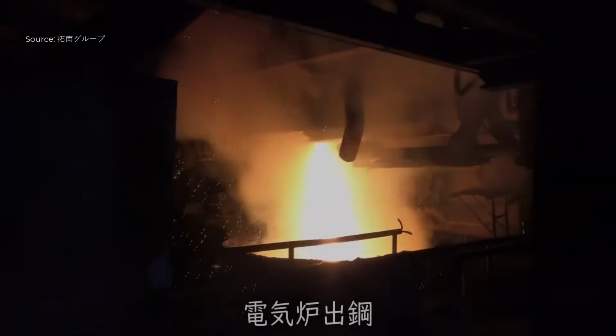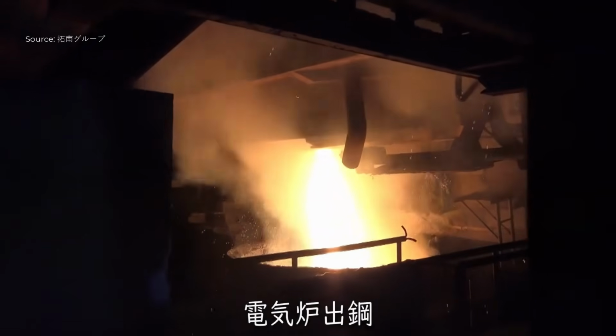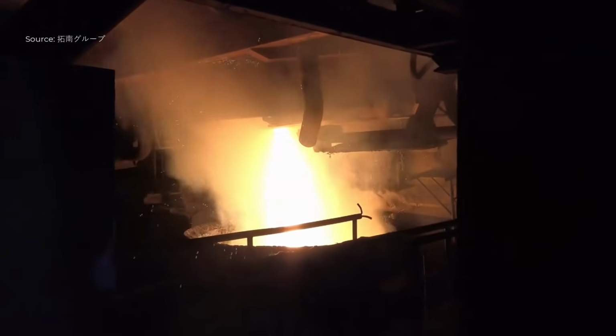To achieve uniform chemistry, argon gas is injected from the ladle's bottom. The rising bubbles stir the molten metal, creating turbulence that evens out temperature and composition. This argon stirring also removes dissolved gases like hydrogen and oxygen, further improving the purity and mechanical quality of the steel.